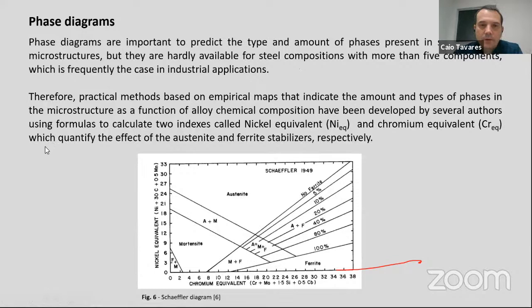So the phase diagrams are very important for austenitic stainless steel, to predict the kind of microstructure that you have. But unfortunately, most of the compositions that we have in the market have more than 5 components. And it's very difficult to find phase diagrams for stainless steel. Basically, what we find in the market are empirical methods, maps that indicate the amounts of the microstructure.